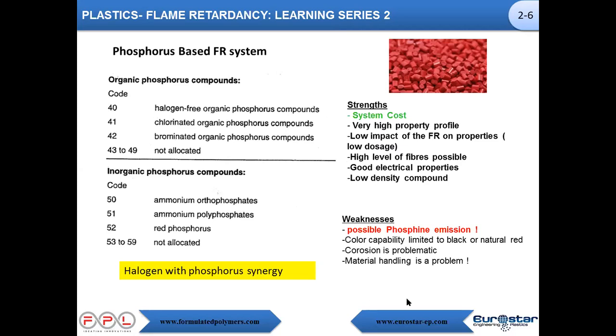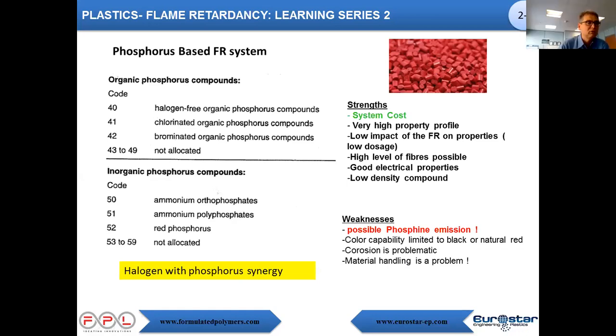Color capability indeed is a problem, because as the raw material is red, you can only have black or natural red. In some cases, we can make dark blue for some customers, and it works quite fine. Corrosion might be problematic, and material handling is a problem. It's a problem mainly on the manufacturing side, but when it's in the form of granules, it's no longer a problem, let's say, for molders. So this was for red phosphorus.